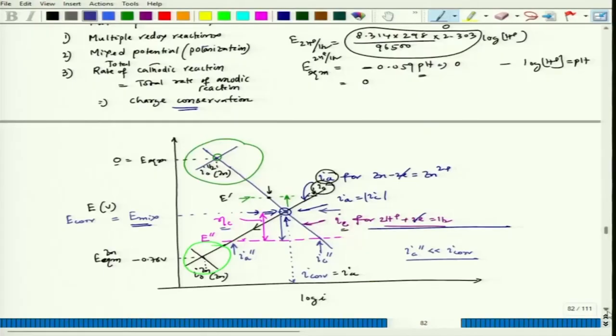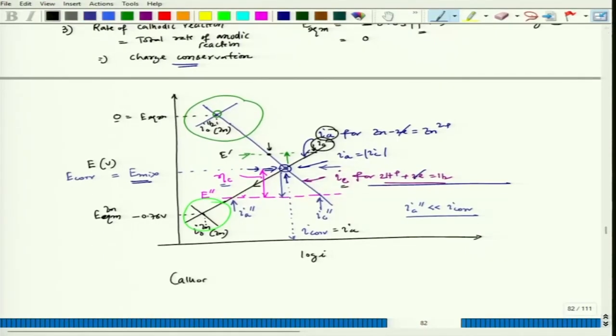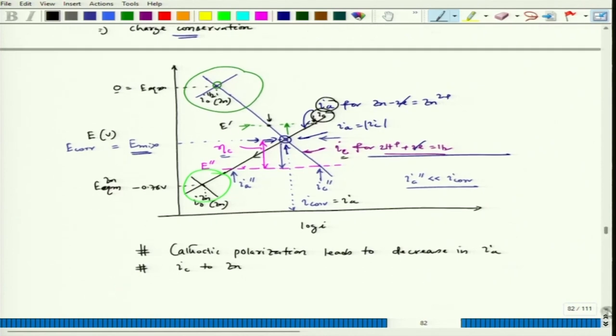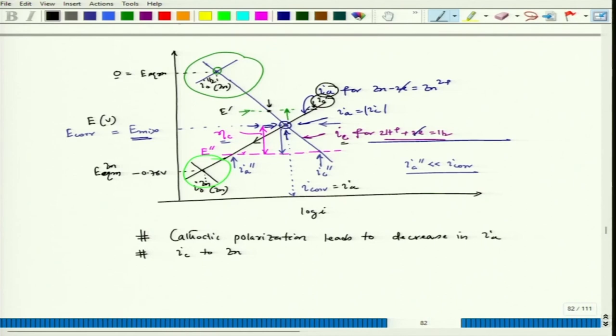So, this is also happening in case of real corrosion system, that cathodic polarization or decrease in IA. And this also happens if we do send negative current to zinc. Now, how can we send negative current? So, if we leave zinc in HCl open atmosphere, then the potential will be E corr, more or less; that E corr will be maintained. So, then how can we actually take the potential down so that I can have less IA? That can be possible if we do two processes.